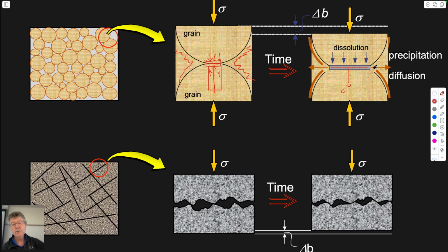So if you look at concentration versus length, then the concentration gradient looks like this. High here because it's dissolving at the same rate along here, but at the central part it has further to go than it does at the edges. So Fick's law suggests that for this axisymmetric case, this would be like a poker chip in plan view. The concentration is largest at the center, and it moves by diffusion by Fick's law. The flux is equal to the diffusion coefficient times dc/dx, dc/dr, I guess, in this case. This would be r. And so that's the mechanism by which it moves.